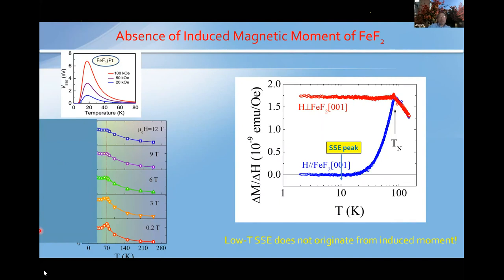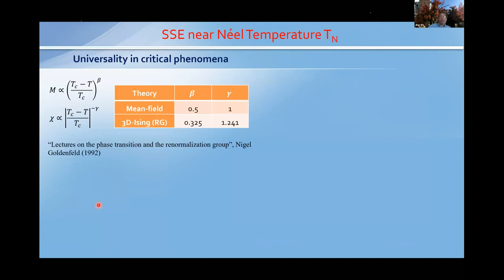Okay, now let me switch to the high temperature peak, located around 70K or so, right? We know that a lot of thermodynamic quantities, including transport quantities, have power law type of behavior at the critical temperature. They typically show universal behavior with a universal set of exponents. So for example, in mean field, we have the magnetization exponent, beta, and the magnetic susceptibility exponent, typically called gamma.